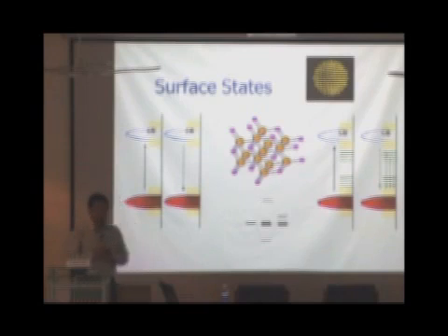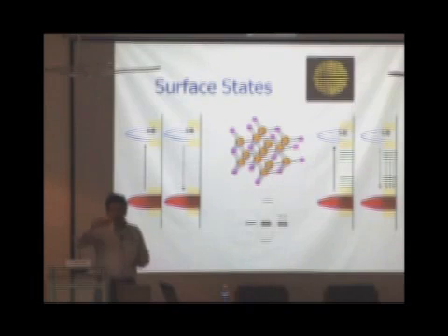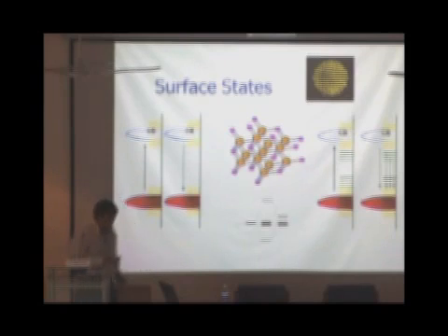So those are called dangling bonds, and dangling bonds means they are electronically placed at more or less the same level where they started with as atomic orbitals. Right? So they are not shifted anywhere because they have not bonded to anything. And if they are not shifted anywhere, they would lie between the HOMO-LUMO, or the conduction band and valence band, so within the band gap region. So these green ones are what I'm showing you as the dangling bonds.